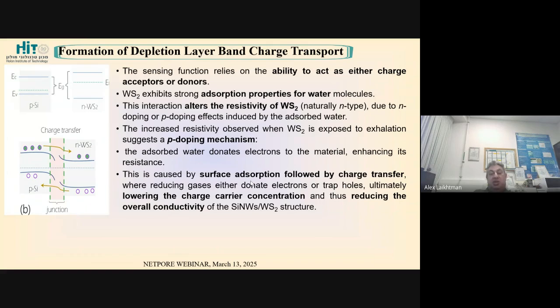So it's a bad thing, for example, for perovskite solar cells, but it's a good thing for breath test. So you see that the same issue can be positive or negative for different types of application. Here, in breath testing, we need to increase the resistivity response. So when there is water adsorption on the WS2, it increases the resistivity, and then the sensitivity of the sensing is also enhanced.